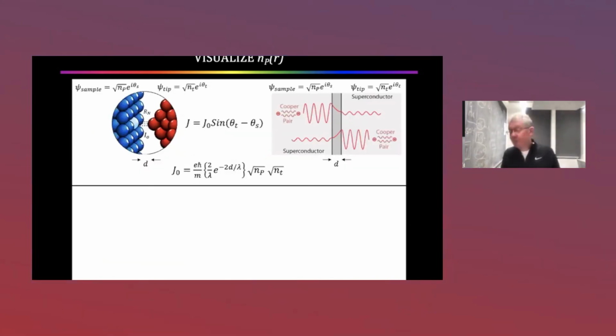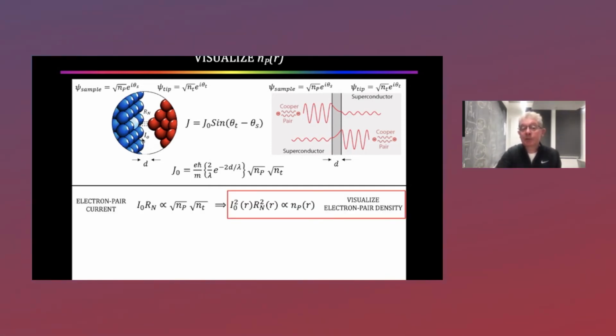And last but not least, we need to visualize the density of electron pairs. And for that, we use scanned Josephson tunneling microscopy, a superconducting sample and a superconducting tip. Under those circumstances, there's a Josephson current of electron pairs from tip to sample. The Josephson current density goes as the product of the amplitudes of the two wave functions, and the amplitude is the square root of the number density. So in Ambegaokar-Baratoff, the Josephson current through this junction multiplied by the normal resistance of that junction is proportional to the gap in the tip and the gap in the sample.